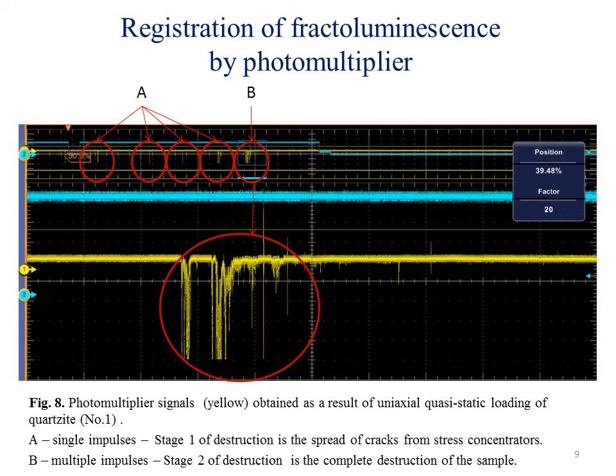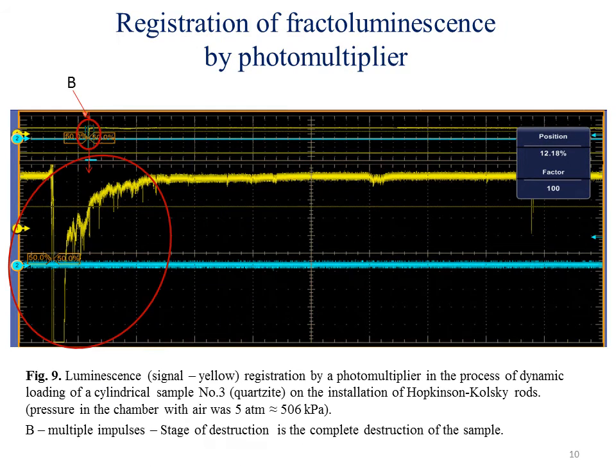A photomultiplier was used to record the luminescence of sample number 1 in the process of uniaxial quasi-static fracture. The destruction was accompanied by single signals and multiple impulses. This is typical for the main crack's initiation in the sample and its complete fragmentation.